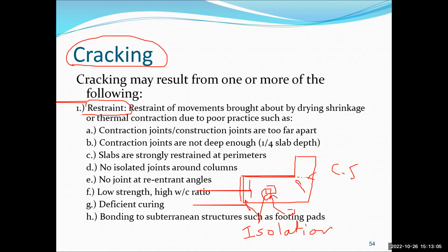So, construction joints that are too far apart. Sometimes what happens when you have slabs is you have to make joints approximately 20-25 feet apart. If not, then the concrete will create its own kind of crack. Contraction joints are not deep enough. Sometimes in concrete slabs, we don't cut the slab all the way to the bottom. We cut it approximately 1/4 of the depth.